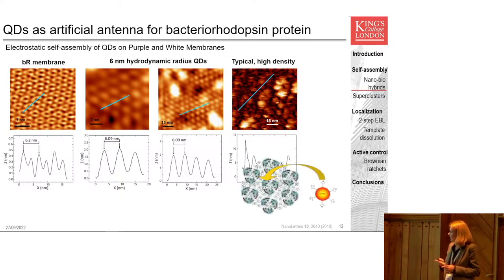And so what is going on here is that the quantum dots, which are negatively charged, are generally electrostatically repelled from the membrane itself, because it is also negatively charged. However, they are electrostatically attracted to the bacteriorhodopsin units themselves, which do have amino groups on the surface of the membranes. And so if our size is just right, then we are able to place approximately one quantum dot in each of those unit cells, and the electrostatic attraction between the protein and the quantum dot is sufficient to hold them there and to form a very nice assembly of quantum dots.